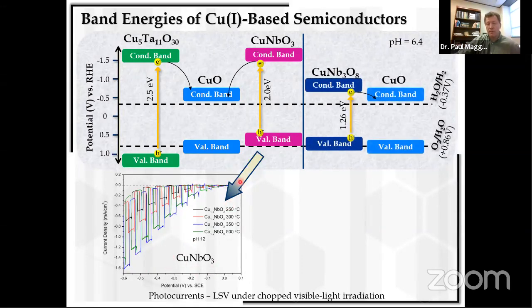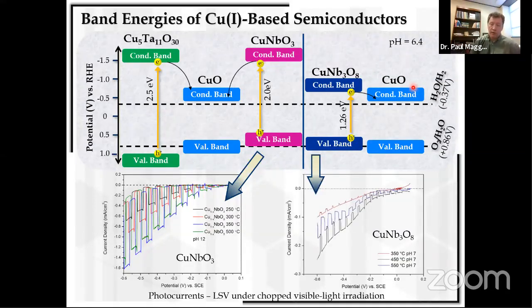But for something with a much smaller band gap, such as the CuNb3O8 phase, there's a much smaller driving force between its conduction band and the conduction band of cupric oxide. So when we measure its photocurrents, they're typically very poor. You see a very high dark current, and it's kind of unstable, and photocurrents are very low. Okay, so this is further evidence showing us that those islands at the surface are important to drive that charge separation.